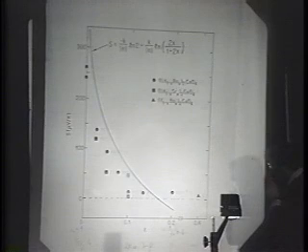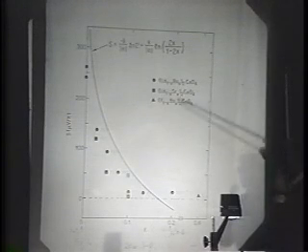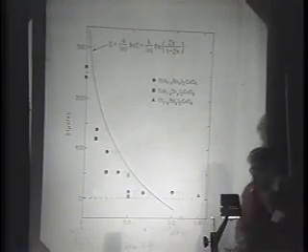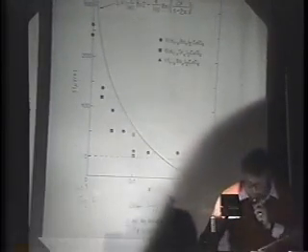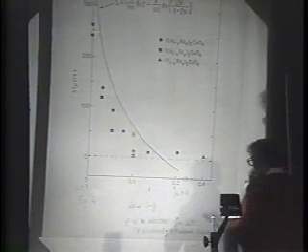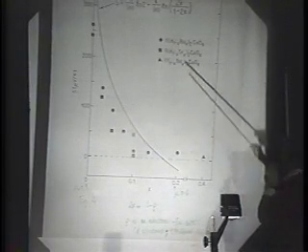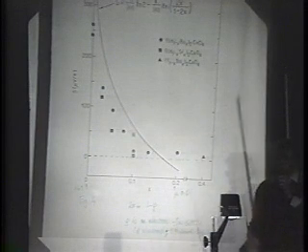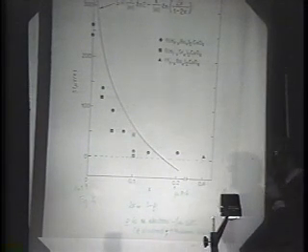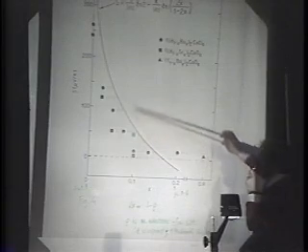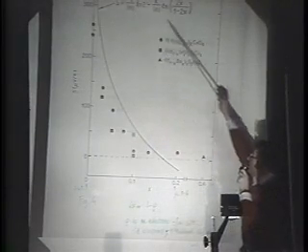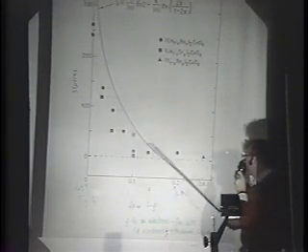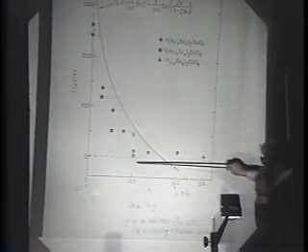And the point I'm trying to make, this solid line is this theoretical formula where you say that you start off with 1 copper d electron per site, and as you add barium or strontium, you're gradually removing electrons from this 1 copper electron per site. And we think as a first approximation, this line, which doesn't contain any adjustable parameters, shows a reasonable description of our thermopower data up to about x equals 0.1.